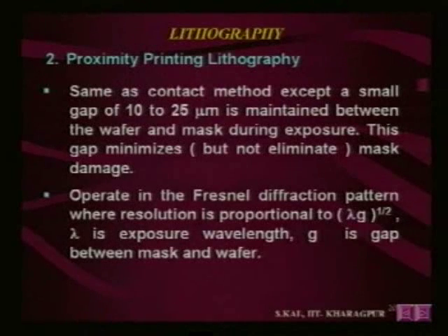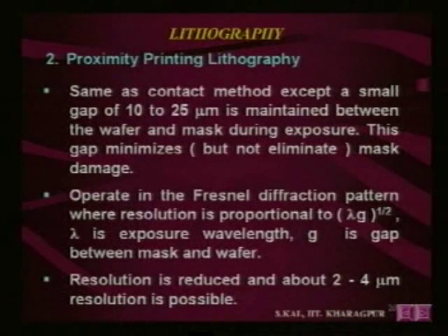Since g is more here compared to the contact printing lithography, automatically resolution here is poor compared to contact printing lithography. The resolution here is reduced, and about 2 to 4 micron resolution is possible, whereas in contact printing lithography you can expect resolution less than 1 micron.